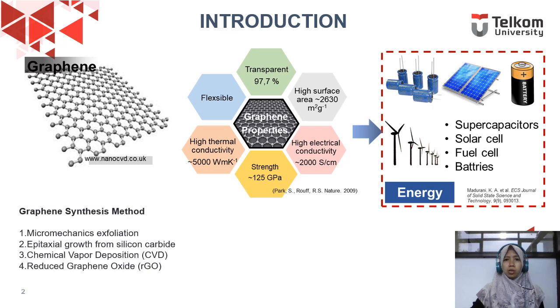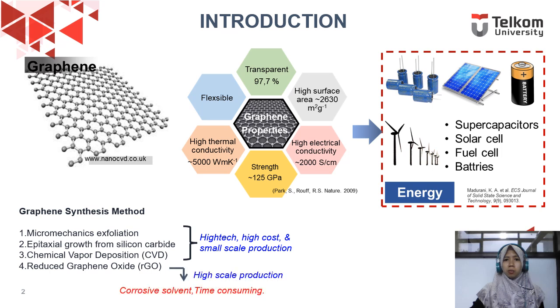There are several methods to synthesize graphene. However, the first three methods need high technology, high production cost, and produce a small amount of graphene. On the other hand, the reduced graphene oxide method produces a larger amount of samples. This method commonly uses graphite as the raw material. The synthesis process begins with the oxidation of graphite to obtain graphite oxide, exfoliation of graphite oxide to produce graphene oxide, followed by thermal or chemical reduction to produce RGO.